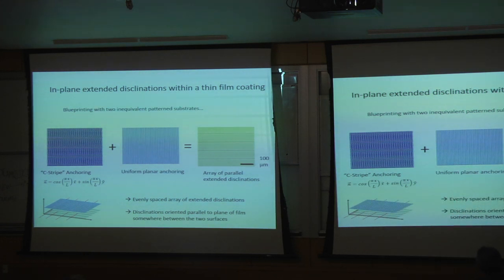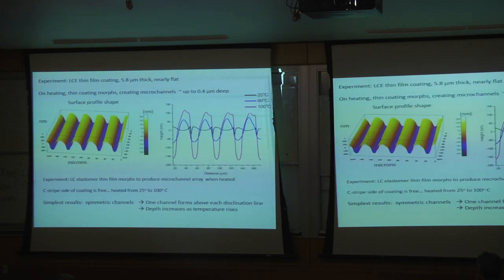So let's see, the C-stripe pattern is on one substrate, the other substrate has a uniform nematic director, and in between we get this array of parallel line defects that are in the middle of the sample that run along the film. And then when that material is heated, you get channels. Now, what could you do with a material where at one temperature it's flat and another temperature you have channels or ridges? Greta Babakanova has used that phenomenon, for instance, to capture colloid particles.